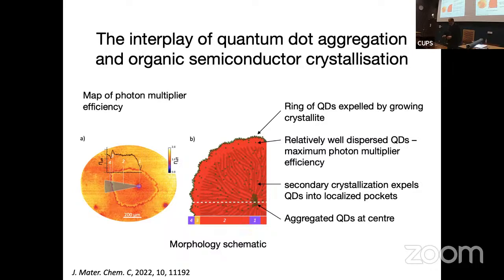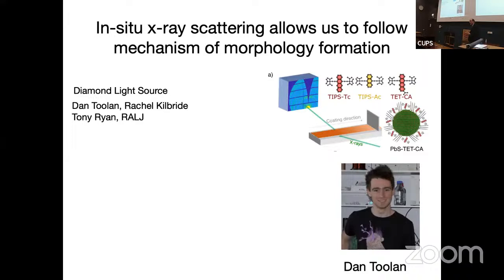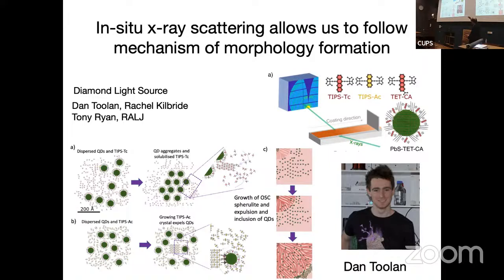And one of the things that we're trying to do, going back to what I showed you before about those light sources, is use in situ X-ray scattering to study the morphology as it happens. So we're doing this at a synchrotron, at Diamond. This is just some cartoons of the different mechanisms we're starting to see about how the quantum dots and the organic semiconductor interact, and how the crystallization of one drives the aggregation of the other. So what we hope is, by understanding this process of morphology formation, we'll be able to work out a way of making these things practically.